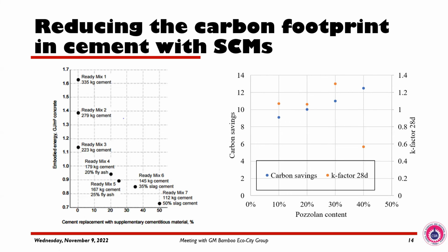So the thing is that, yes, you are making carbon savings, but when you go above 30%, your efficiency factor falls down. So that one should give you a key to how to optimize your material. With this clay that I used to produce my pozzolana, my optimized material was at 30%. Some clays can optimize the material above 30% when you look at the efficiency factor. It is a very key thing when you are doing this kind of work.